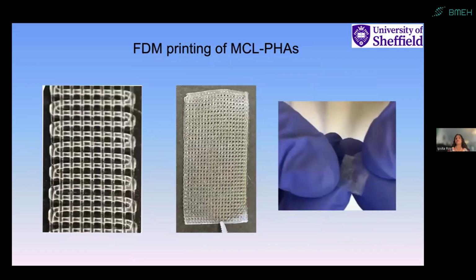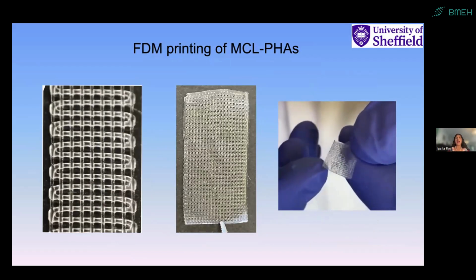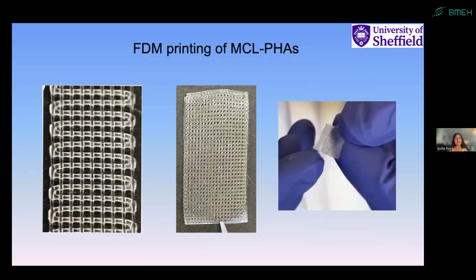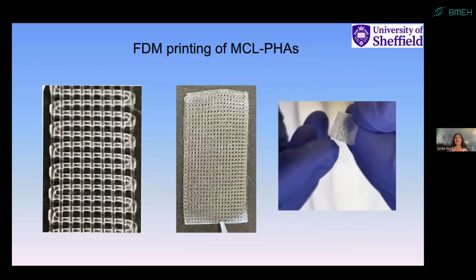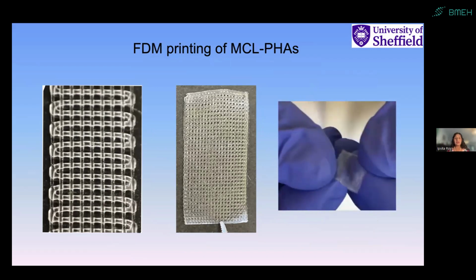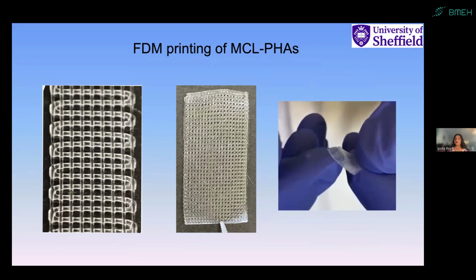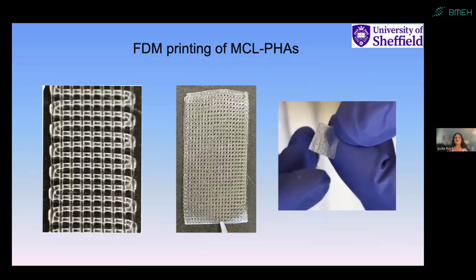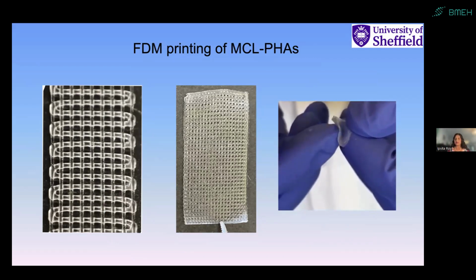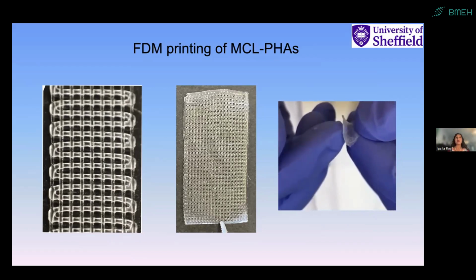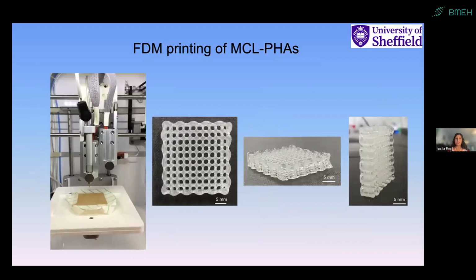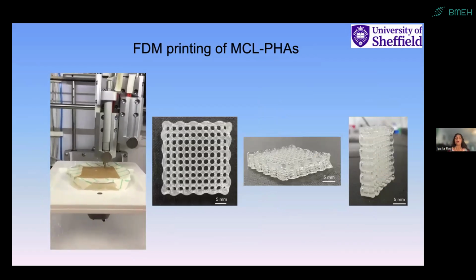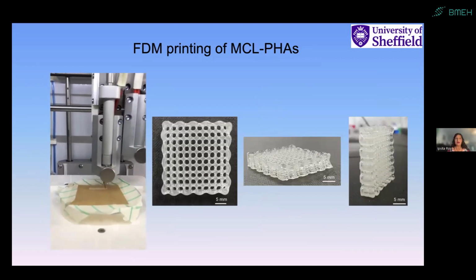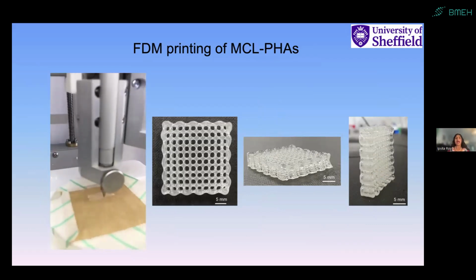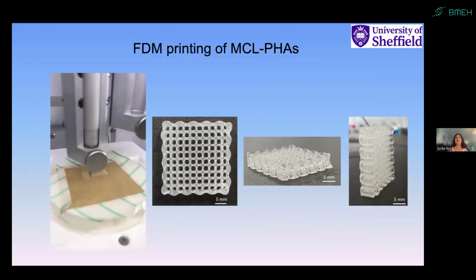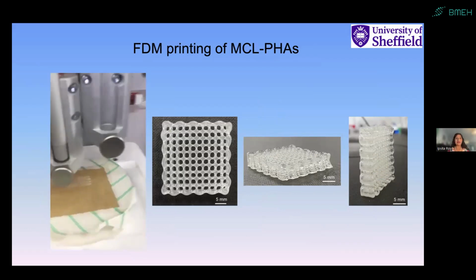So there are many different processing methods that we have used, and here you can see the FDM printing of medium chain length PHA, and you can see how beautifully elastomeric and so malleable it is, and it is also very suturable once it's 3D printed. So this is 3D printing of MCL PHA. This is yet another MCL PHA, not the same one as you saw before, that we have managed to 3D print, and you can see that the structures are very, very clearly defined and robust.